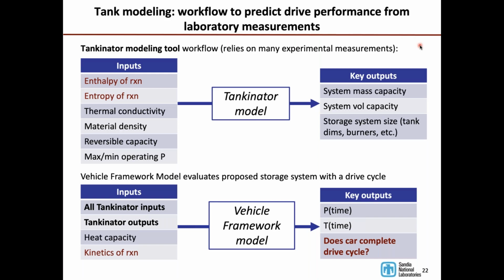This code requires a couple of key inputs, the thermodynamics, as I'm showing up there, the enthalpy and entropy of reaction, and the thermal conductivity, along with some other things. You run that code, and then that outputs the system capacity, mass, and volume, and some information about the system size, and then you put that into the framework model. And the framework model adds one extra dimension, which is the kinetics of the hydrogen release. So the strategy here is to design this tank based on the materials that we're looking at, put that in a framework model with kinetics, and then run the framework model and ask the question, does the car complete a drive cycle? So that's the strategy.